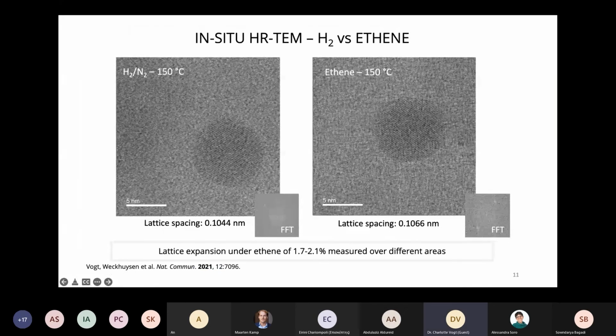So again, different areas here. You can see a different nanoparticle that we measured. We really were able to obtain very nice lattice structure, and this is really because we used this approach. So we had our MEMS reactor, of course, and directly onto that silicon nitride membrane, we deposited these nanoparticles, and this allowed us to get basically lattice fringes, and to be able to see this expansion.